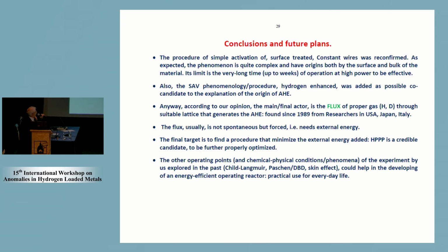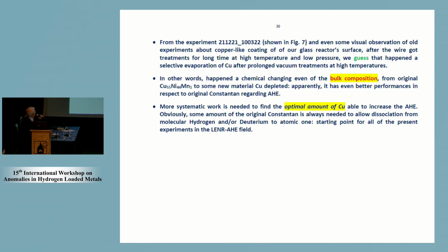Conclusion: the flux, again, according to us, is the key parameter. So as fast as possible. But flux means some energy added to move the gas inside, so we have to minimize the extra energy needed to get flux. And we got information just by chance that using vacuum it's possible to change the bulk composition of the material. It means the copper was depleted. We have proof of this point.